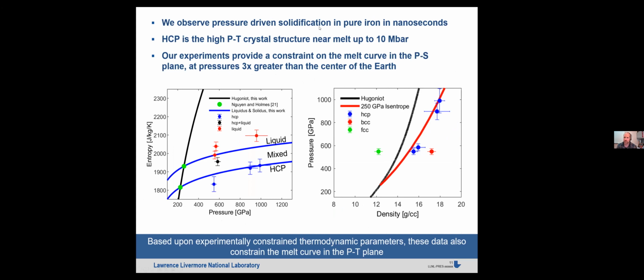So again, as I showed in those first two examples, we observe pressure-driven solidification in pure iron on the nanosecond timescale. That implies a couple of implications. One, that you'll solidify from the bottom up, and then also there's questions about whether or not homogeneous nucleation is the relevant model, and therefore, is the core nucleation paradox really a paradox? We also observe HCP as the equilibrium high pressure temperature crystal structure along the melt curve up to 10 megabar.